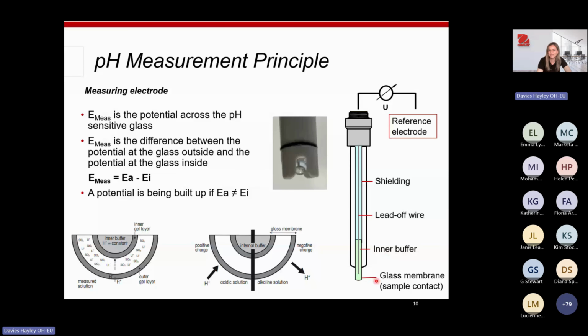So the glass membrane is kind of the most important thing on the electrode. We mentioned that the special type of glass reacts with an aqueous solution, and it forms a gel layer. So you will form a gel layer on both the inside and on the outside of the glass. And that gel layer acts like a sponge for hydrogen ions, or H+ ions. And those H+ ions can either diffuse into, or diffuse out of the layer, depending on the pH